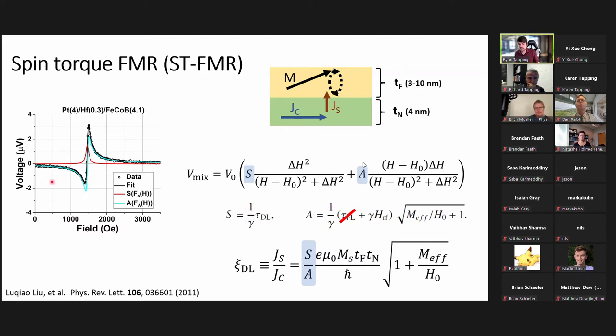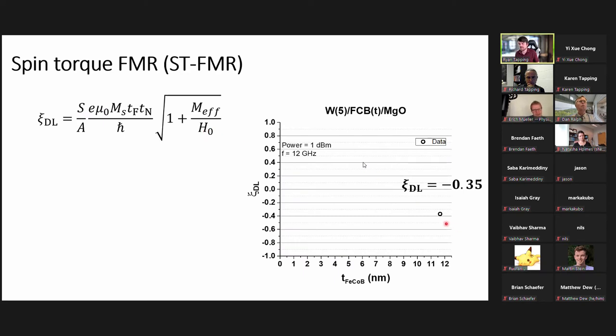What does the data look like? When we collect a field sweep from 0 to 3000 Oe, the raw data in black is fit to extract the symmetric component in red and the anti-symmetric component in blue. By using those fits and plugging in the numbers, we get the damping-like spin torque efficiency. As an example, I plotted one point here: a damping-like spin torque efficiency of minus 0.35, which is a little large. Tungsten is usually around minus 0.3 and platinum around 0.1 from the literature.